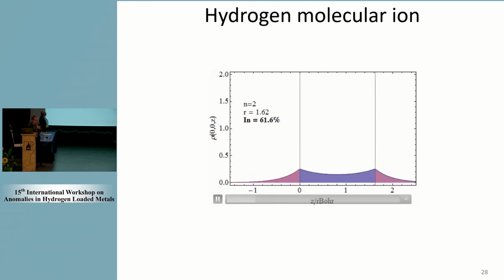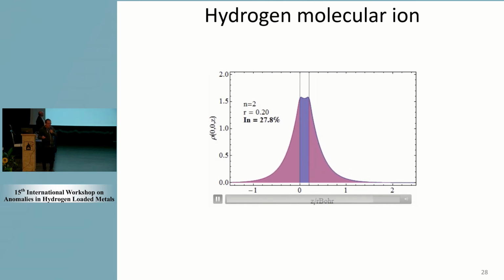Oh, it does. Okay. So we tried to make some progress on the theoretical side as well, trying to explain these large electron screening potentials that we measure. The idea is to look at the hydrogen molecular ion and calculate the electron wave function within it. Then we took the probability to find the electron in between the two protons or deuterons. We assumed that if the electron is between the two, then the screening is complete, so you have no Coulomb barrier.